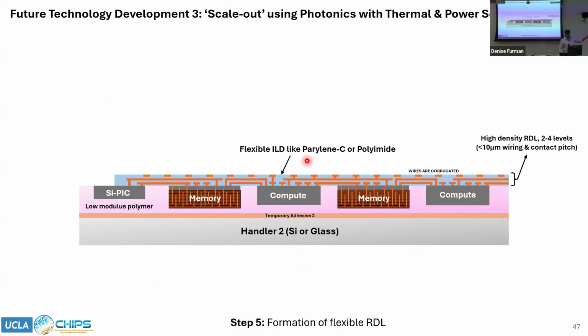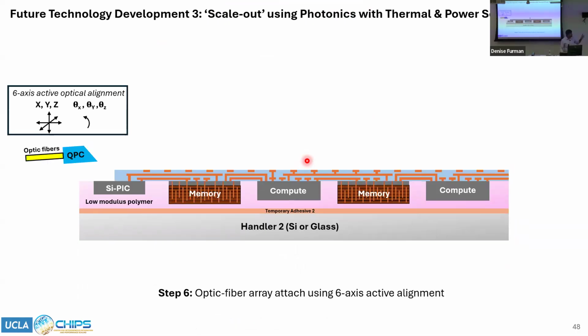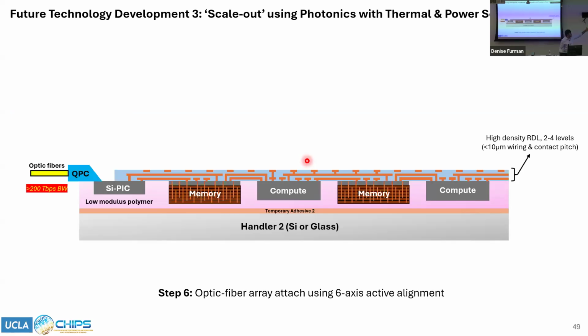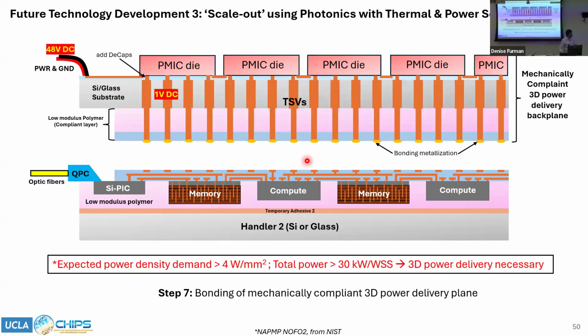And then we debond the first handler, and then we can define the RDL on top using the TrueAdapt process I mentioned earlier. And you can also have a little space here for attaching the fiber optic connector. So then you can do a 6-axis optical alignment using active alignment to attach, for example, here I've shown a QPC, a quasi-planar coupler, to attach optical fibers to enable high-speed data communication.